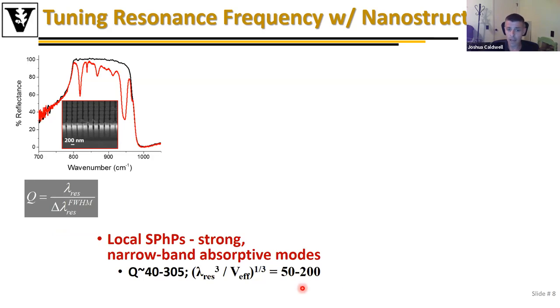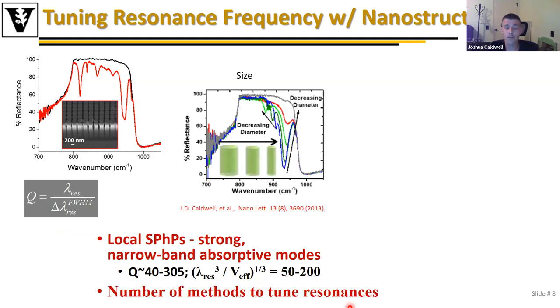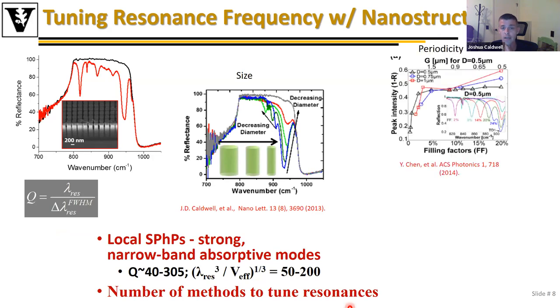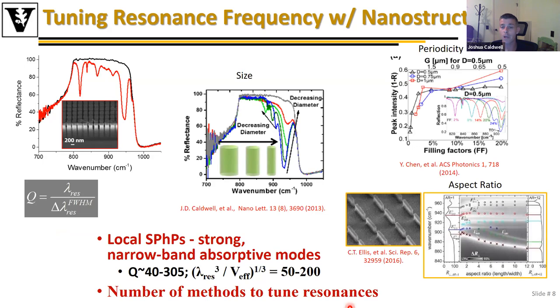But they also have a very high modal volume, a very small modal volume, right? So this could lead to large potential for Purcell factors for enhancing optical processes. And they're fully tunable, as I showed you before, by changing the material, I can change which spectral range I'm operating in. But of course, changing the size, shape, the periodicity of these structures, or aspect ratio, I can dictate how these resonant modes, where they occur within the Reststrahlen band, and what their modal polarization, as well as profiles look like.